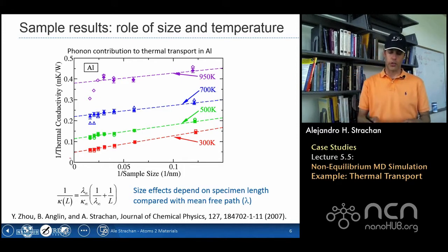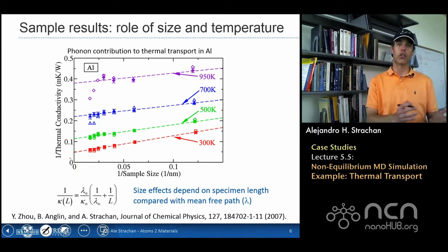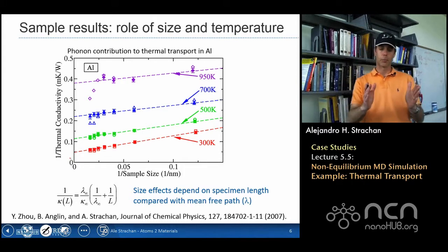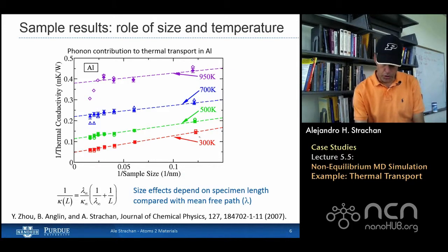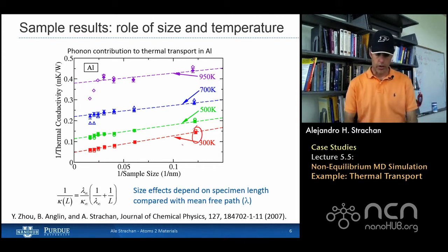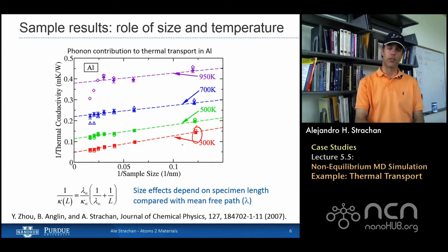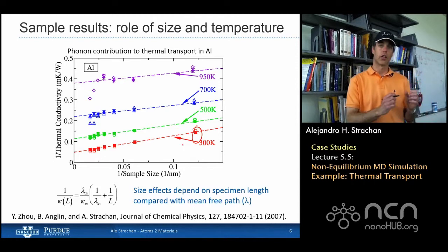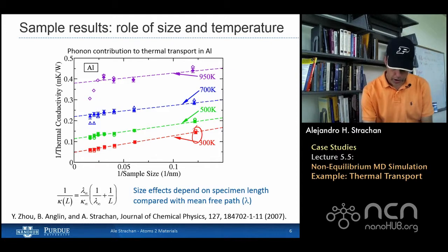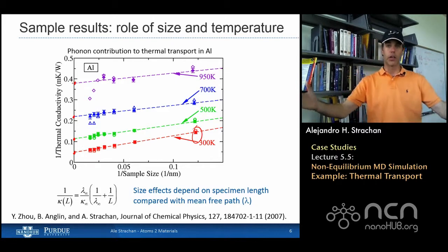The other interesting thing that you see here is that for a given size, the thermal conductivity is size dependent, okay? And the reason why it's size dependent is that the specimen size limits the maximum mean free path that the phonons can have. Of course, it also limits the maximum wavelength. But it's the mean free path that governs these size effects that you see there. And that's why what we find is that, again, this is inverse sample size. So on the right, we have small samples with high resistivity. As we move to the left, the conductivity goes up as we increase the size. If we extrapolate to zero inverse size, this would be the bulk, infinitely large materials.